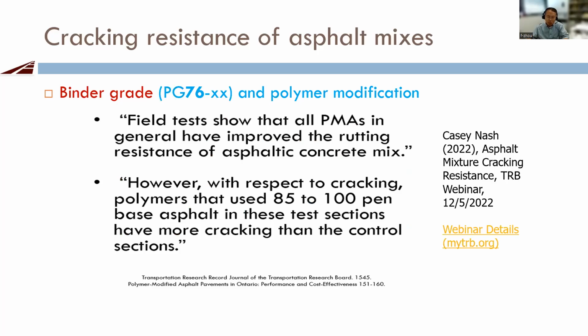And another thing I just want to warn everyone: increasing your binder grade at the higher end or using polymer modification may not guarantee improved crack resistance. So this is from Casey Nash from Maine DOT, from one of his slides. He said the field tests show that all PMA in general have improved rutting resistance. But in terms of cracking, polymer-modified sections that used 80 to 100 pen-based binder in these test sections have more cracking than the control section. So he cited this from a TRB publication.